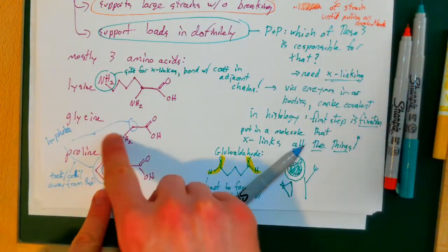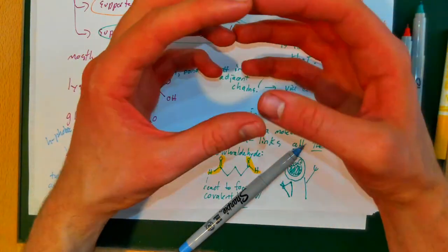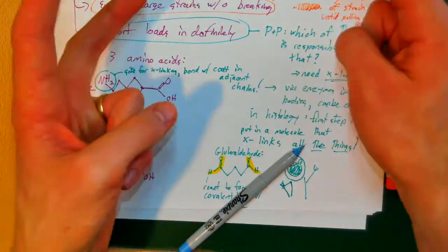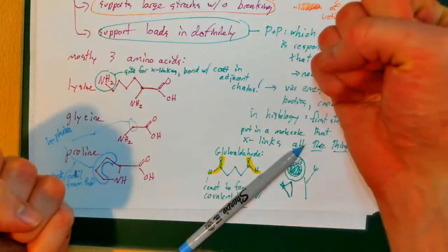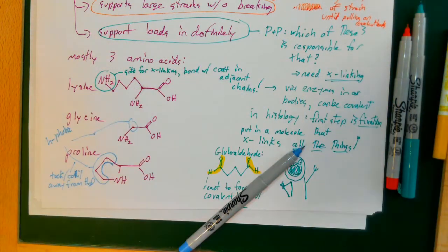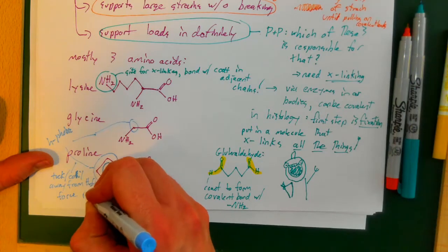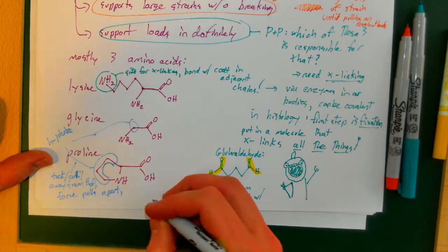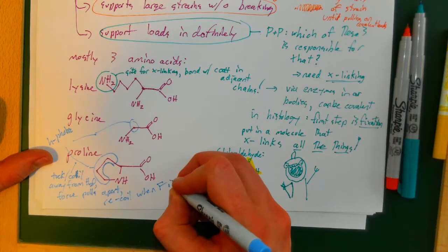This tucking and coiling effect gives the elastin some natural state that's kind of condensed like this. But when I go to stretch my finger, I can uncoil all of those tucked away hydrophobic regions. They don't want to interact with the water, but they will if I stretch them out a little bit. And once I've released that load, they want to tuck themselves back together to avoid water. So they tuck and coil away from water, force pulls apart, and then they recoil when force is removed.